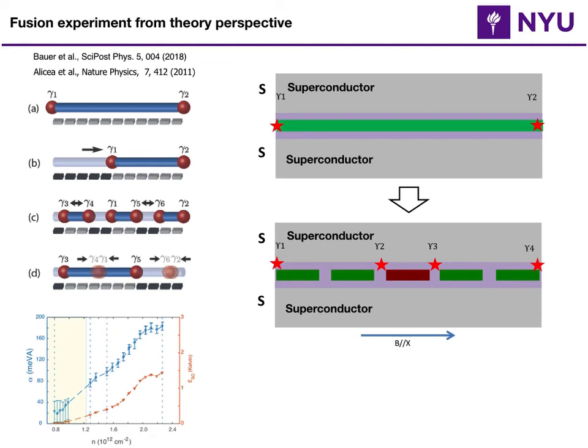Very early on, Jason Alicea and Bella Bauer came up with this keyboard proposal on nanowires, that if we can tune the gate voltages in a keyboard under the nanowire in the right configuration, you can think of the Majorana wire as effectively changing width, right? So if you go from A to B, you can shrink the length of the wire, and by creating the gate voltages on the left side, you can make this other segment between gamma 3 and gamma 4. So once you can move and you have two pairs, in principle now you can merge them together, right?